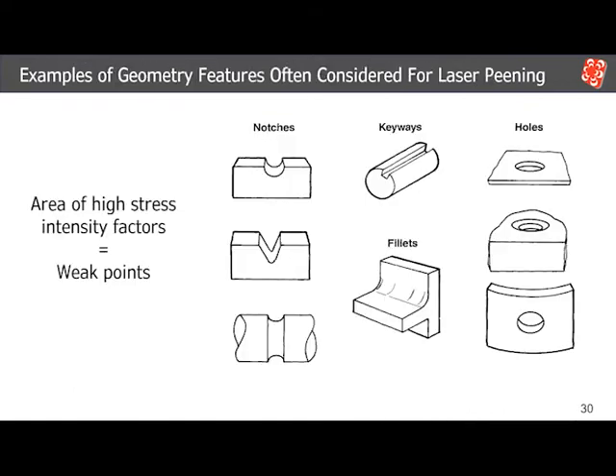So in general, for industrial application and industrial parts, a lot of the parts that we receive suffer from the same problem, which is a feature with a high stress intensity factor. Examples are notches, fillets, and holes. These high stress intensity factor locations are the weak points in that component. And by applying tensile stresses, that's how you're failing it and causing the fatigue crack to start and propagate.